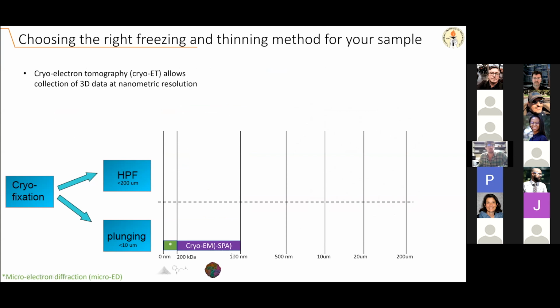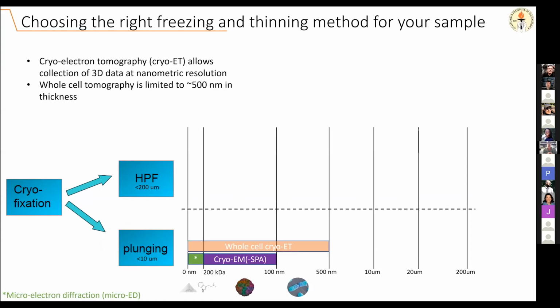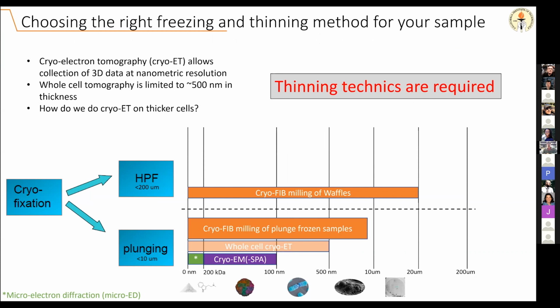Liza touched about single particle CryoEM, mainly that deals with samples that are approximately 100 nanometers thick. Wholesale cryo-electron tomography, meaning I can just plunge freeze my cell and stick it under the CryoEM, can be done with cells that are at a maximum 500 nanometers in thickness. And when I say 500 nanometers, I'm stretching it a little bit. It's usually less if you want to get good quality tomograms. So what do we do when we have samples that are thicker than 500 nanometers in thickness, which basically means every sample, every cell, except a few bacteria? Well, we need to resort to thinning methods.